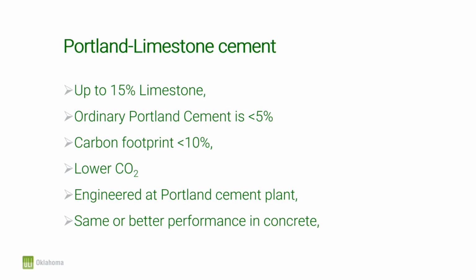What it's doing is optimizing that clinker from the cement manufacturing facility. They're also changing their proportions, different proportions of that limestone, iron, silica, and alumina, so that we don't lose any of the other properties that we need for building with concrete. So we maintain the same workability, finishability, and the same strength just by changing the chemistry of it, okay? And that reduces the carbon footprint all by itself.